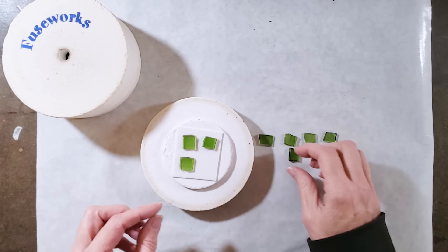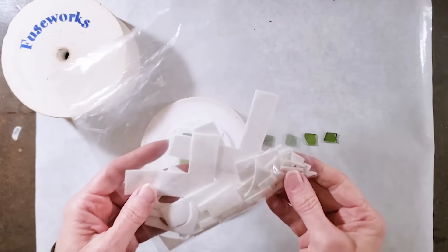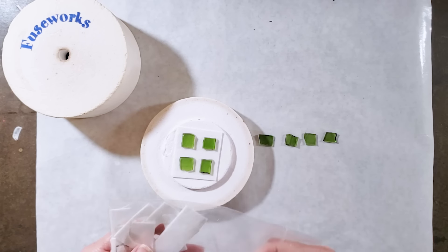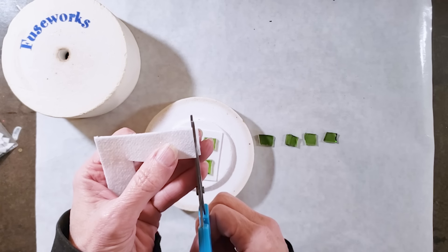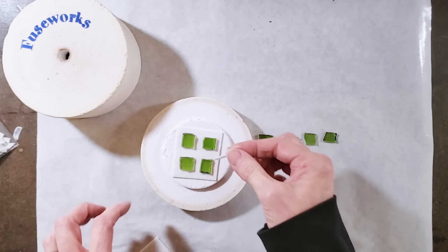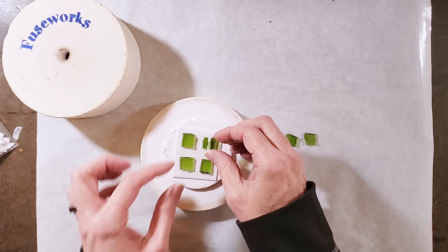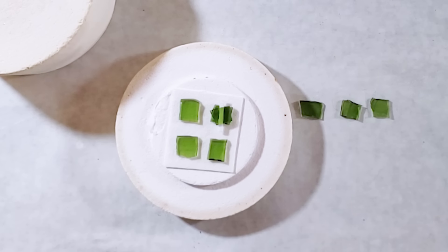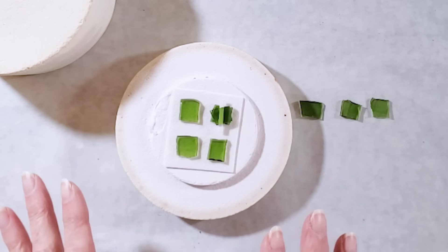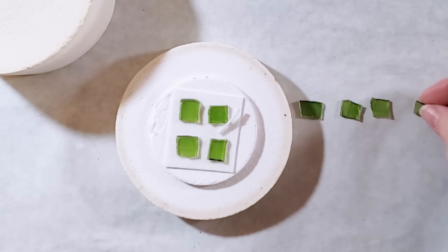The first method: just take your pieces of glass and space them out so they don't fuse together, then cut a very thin strip of fusing paper to lay between the glass layers. Cut a very skinny piece of fusing paper, lay it on top of the first piece of glass, then place another piece of glass on top. Offset the corners a little bit so the shape will become more rounded instead of having pointed edges. This will work and you will get a small hole in the bead.